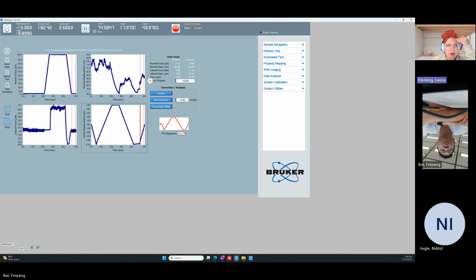I would argue that this is probably the normal displacement here at the end of the test, which is about 30 nanometers versus 0 at the beginning. So we probably scratched a 30 nanometer scratch into the sample. That's probably what's left on the sample surface. So you can go through and get that kind of information, right? You can look at what happened and at what points. Let me grab